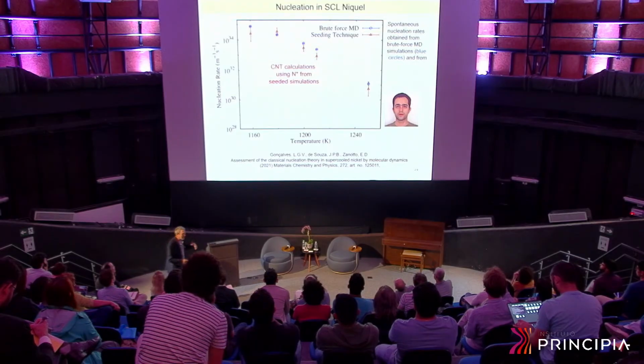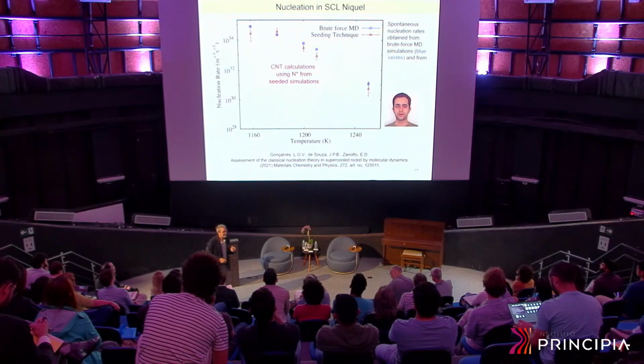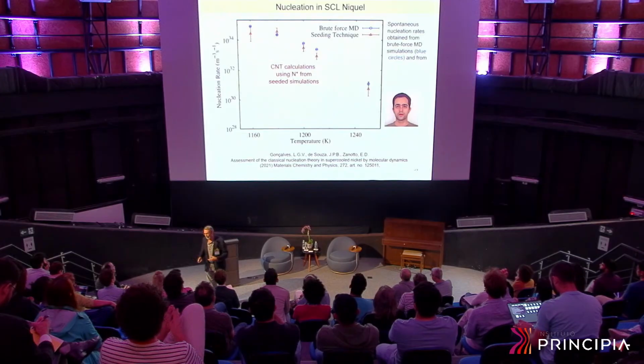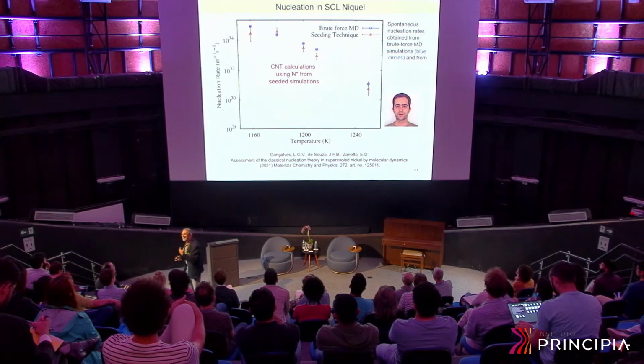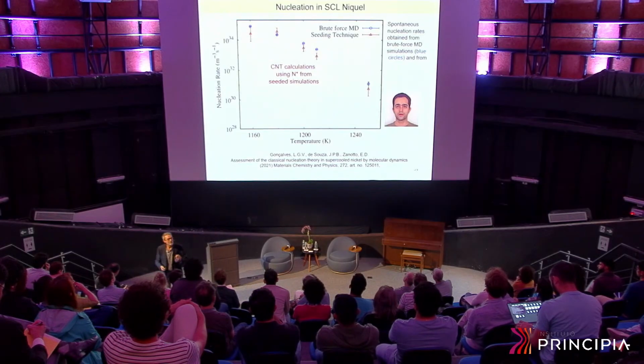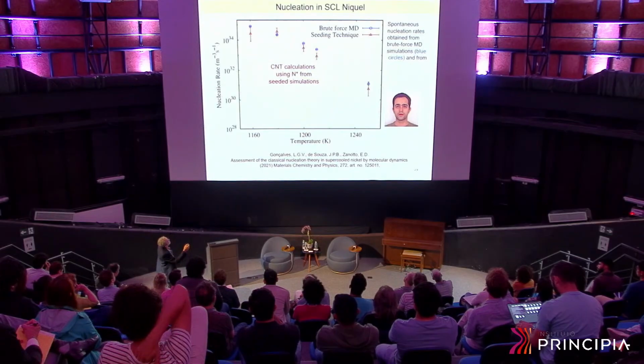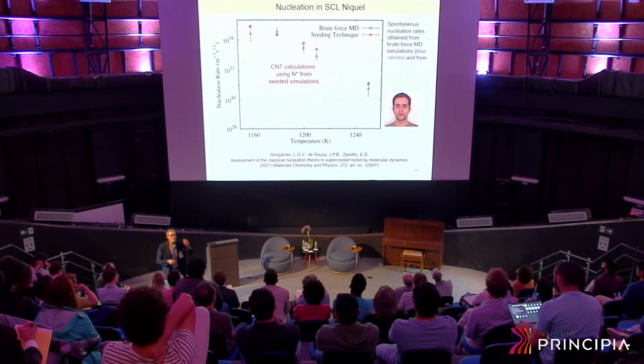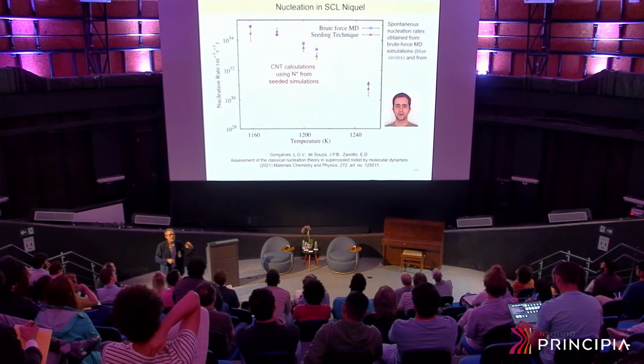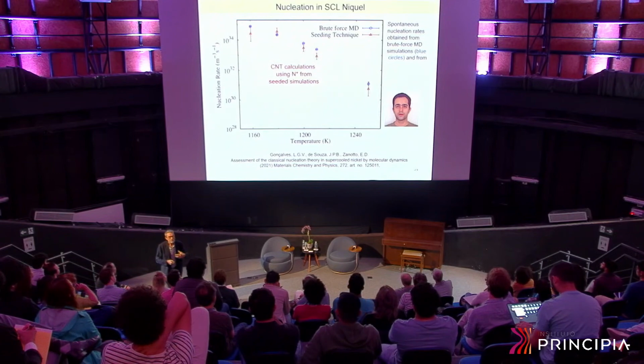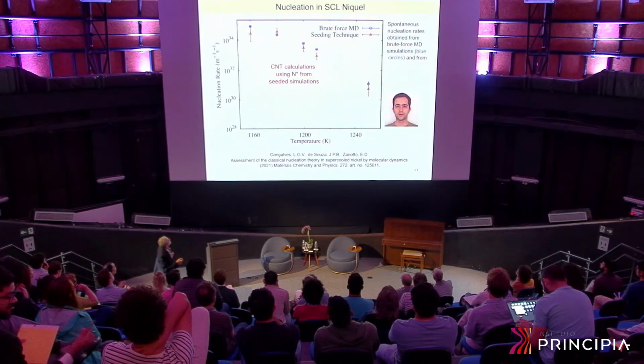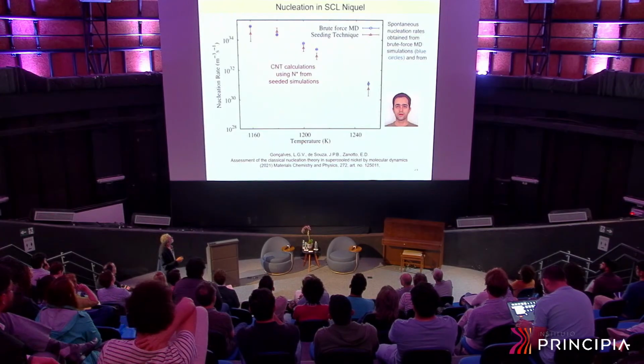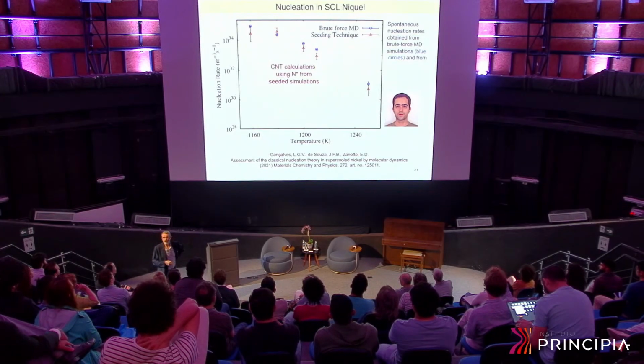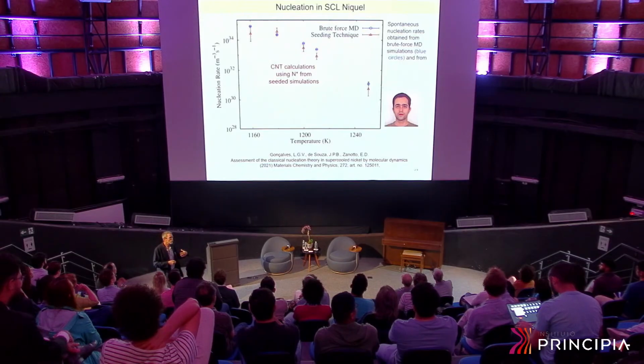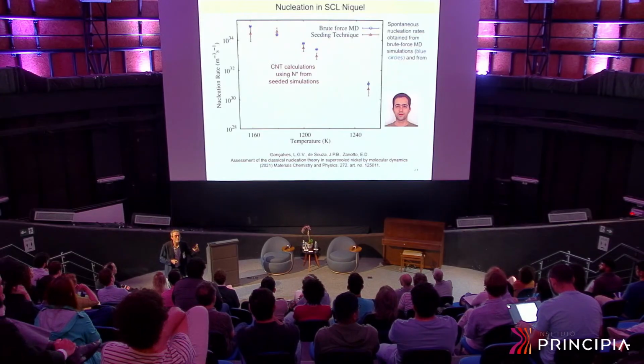But there's always a reviewer that says, well, these are all calculations. You have to compare with experimental data. So we found a system, nickel, for which there was a very reliable potential. Many people are interested in nickel in the metallurgy field, and some people had measured nucleation rates in nickel. So let's try to do MD simulations and compare with measurements.